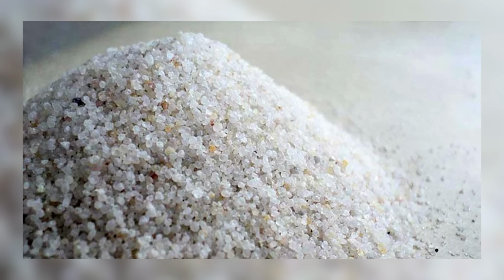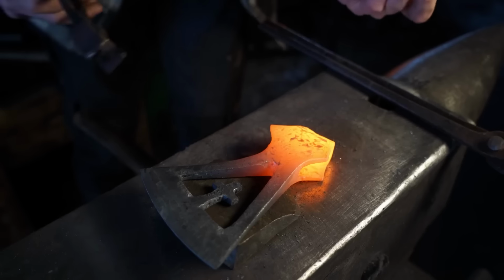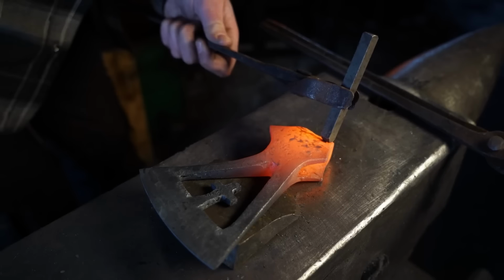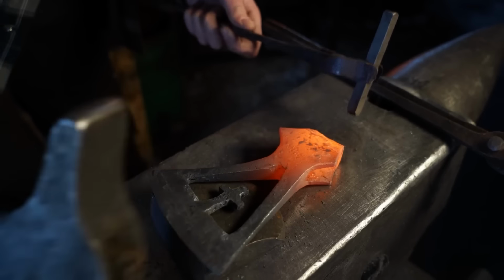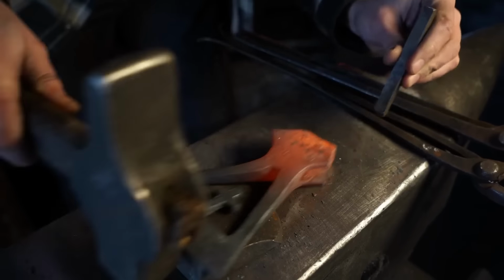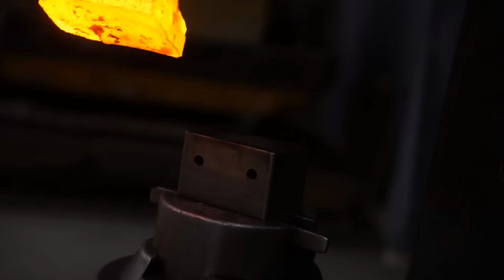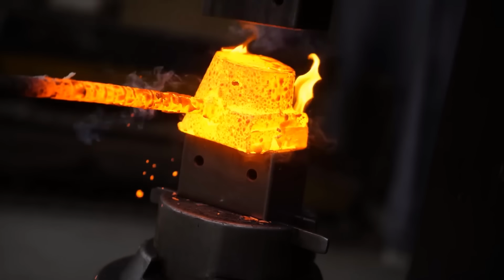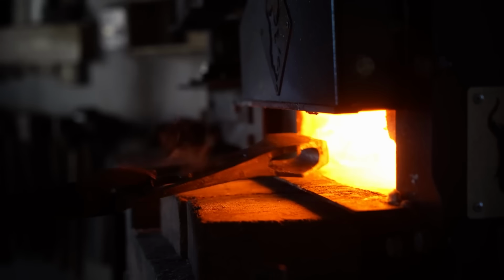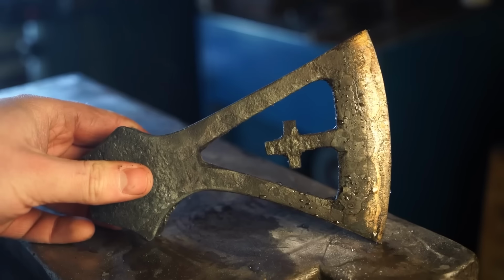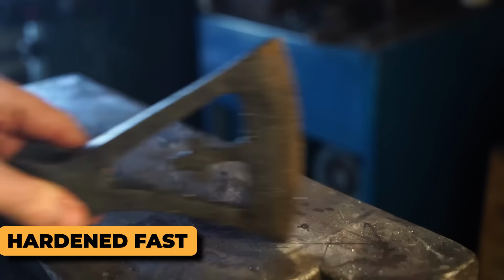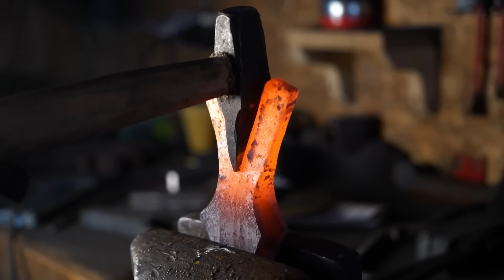But here's the part nobody romanticizes. Sometimes the weld failed completely. One wrong tap with the hammer, and your carefully folded blade split open like a cracked biscuit. That meant reheating, re-welding, and praying to Thor you didn't ruin the temper. And every second the iron cooled was another second you lost control. The metal hardened fast, and by the time you blinked, you were beating cold steel, useless and brittle.